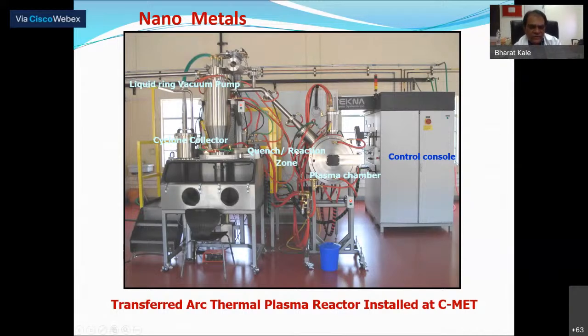In the plasma system, the temperature goes to 3000 degrees centigrade. One part of the reactor is the cathode here. Suppose you have to make aluminum nanopowder, then you can have an aluminum cathode, the temperature goes to 3000 degrees, and the aluminum gets vaporized and quenched at the molecular level. The quenching temperature determines the particle size. If a particular size is required, we can optimize the quenching temperature and quenching time.